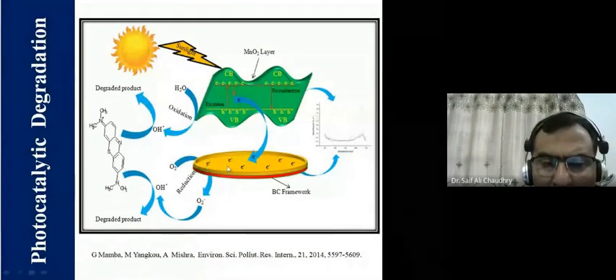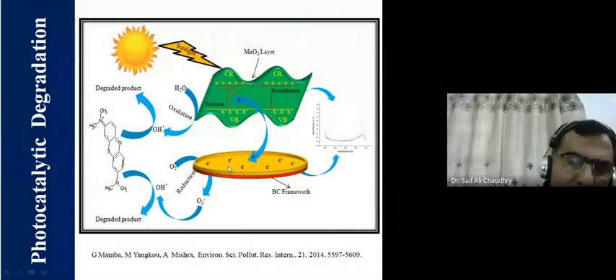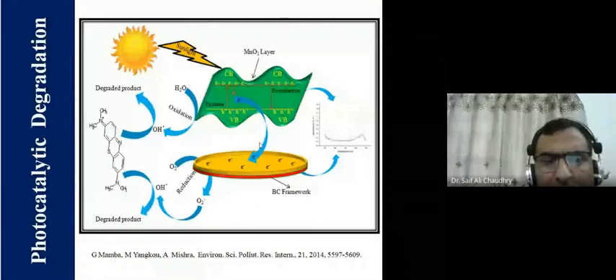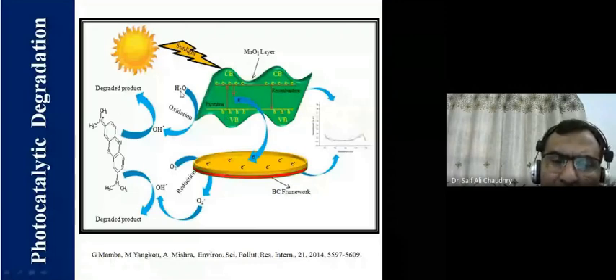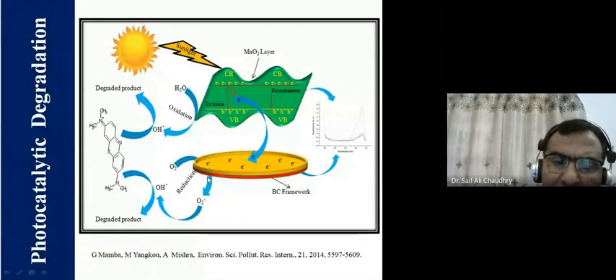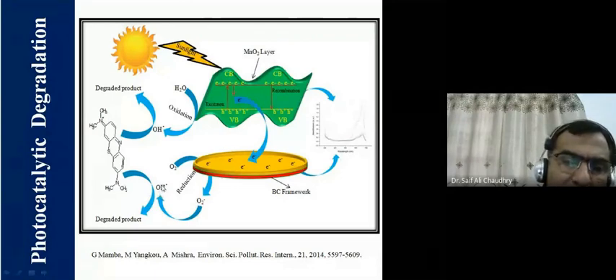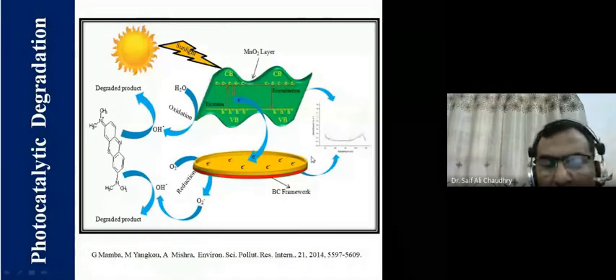Now the mechanism has been proved. These electrons are available on the black cumin surface, and they get excited to the higher conduction band, creating a positive hole here, and water interacts in between and undergoes oxidation, creating OH. This OH directly attacks the methylene blue molecules, leading to their degradation. Again, O2 is also there, and that gets reduced to O2 negative, and ultimately to OH free radical, leading to attack of this OH free radical on the dye molecules and ultimately degrading the methylene blue dye in this case.